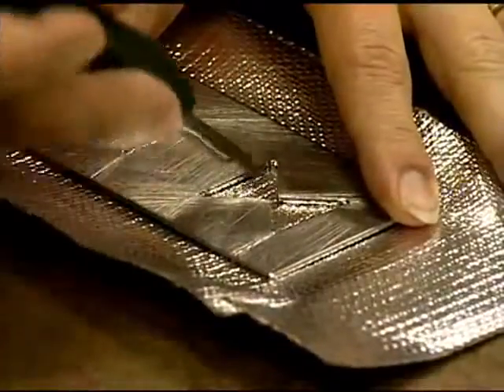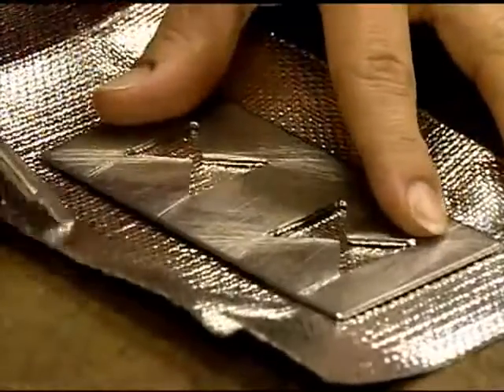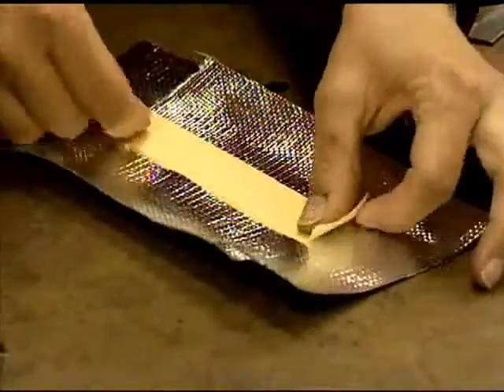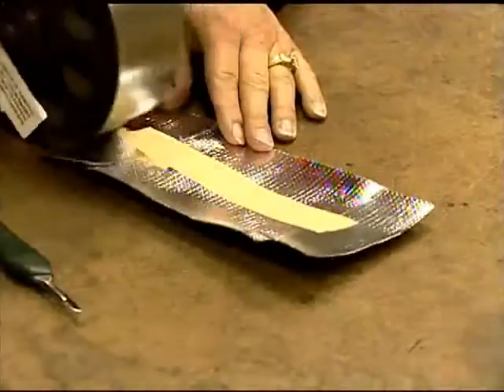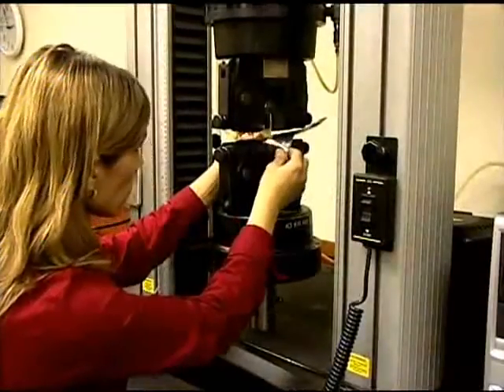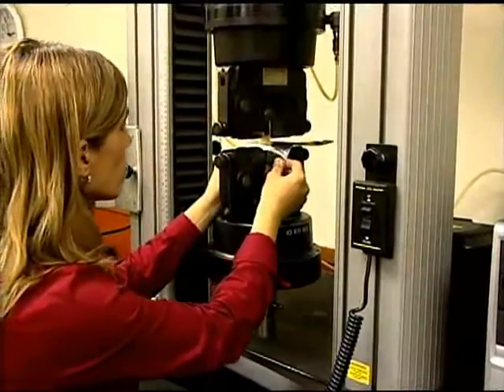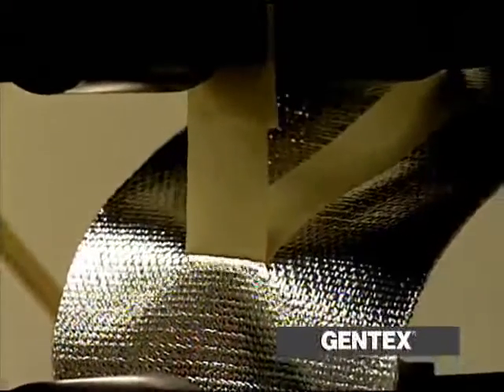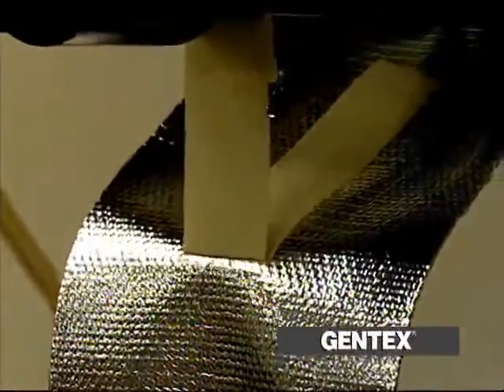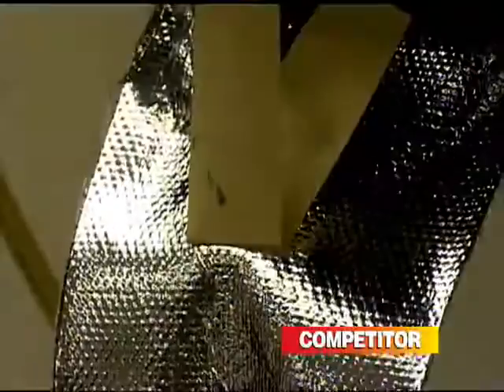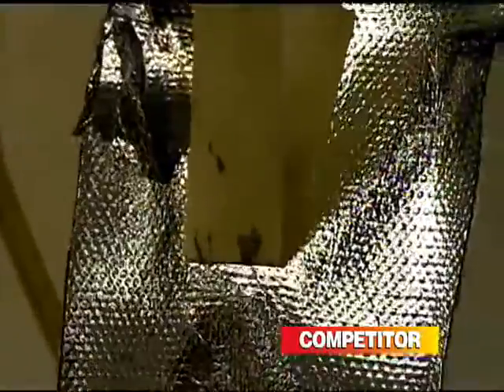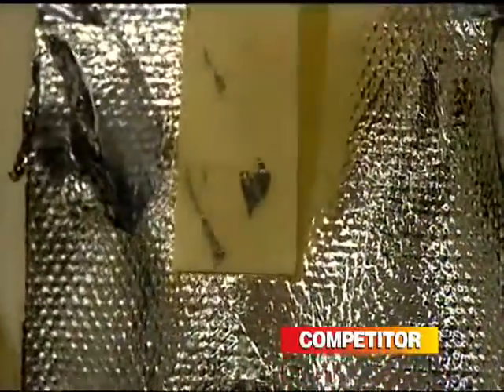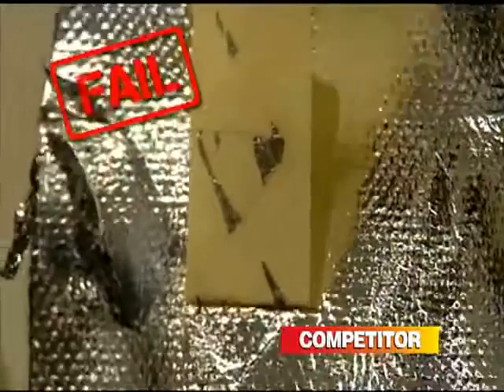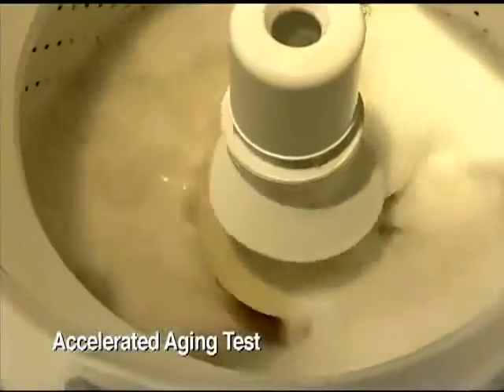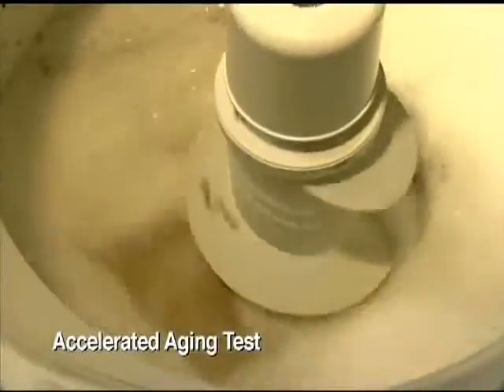The aluminized surface is next intentionally cut in a crosshatch and taped in an attempt to peel the surface away from the fabric. To pass this test, there cannot be any visible delamination or aluminum on the peeled tape. Notice that the Gentex sample does not exhibit any of these signs. In contrast, when the competitor's fabric was tested, there were signs of delamination after wet flex, and you can see aluminum on the tape.